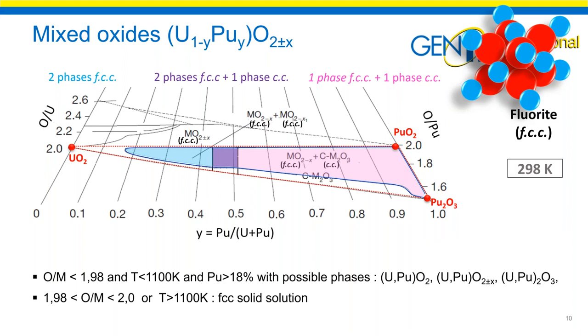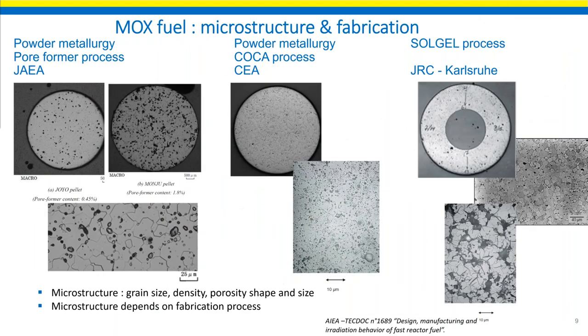So I have no time to present all the fabrication processes available for the MOX pilot fabrication. I just want to illustrate the different microstructures obtained. A microstructure is defined by the density, the grain size, the porosity shape, and the size of pores. So I've chosen three cases. On the left side, we have the Japanese MOX fuels fabricated with a standard powder metallurgy process, but with a pore former that leads to large grains and large pore diameter. In the center, we have our French industrial CoCa process based on powder metallurgy that leads to a very homogeneous MOX fuel with a single phase. And on the right side, a more innovative process based on the internal gelification called sol-gel that avoids powder metallurgy and associated dust, with also very good homogeneity.